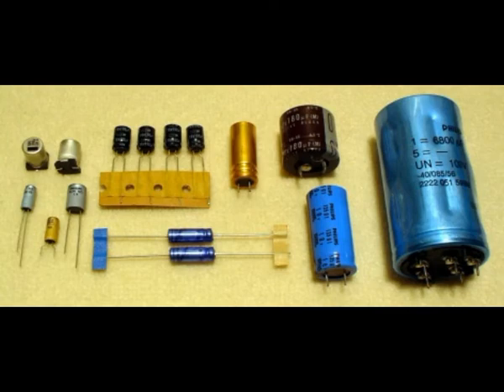The lifetime specification of an electrolytic capacitor is, for example, 2000 H, 105 degrees Celsius. The capacitor's lifetime at 45 degrees Celsius can be calculated as 128,000 hours, roughly 15 years, by using the 10-degree rule. Although the result of the longer lifetime at lower temperatures comes from a mathematical calculation, the result is always an estimation of the expected behavior of a group of similar components.